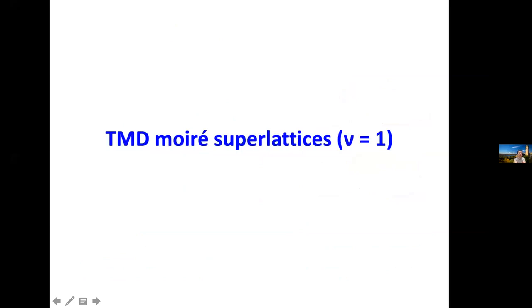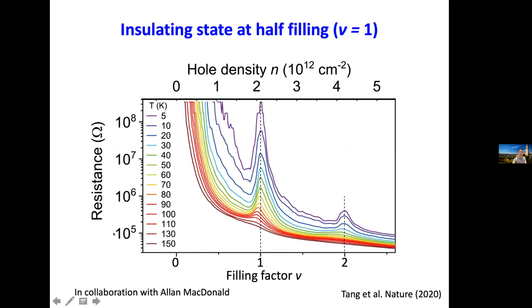First I would like to focus on what's happening when you dope one particle per superlattice site, that's half filling of the first moiré band. This is in-plane resistance as a function of filling factor at different temperatures. At low temperature, you see there are two prominent peaks at filling 1 and filling 2.